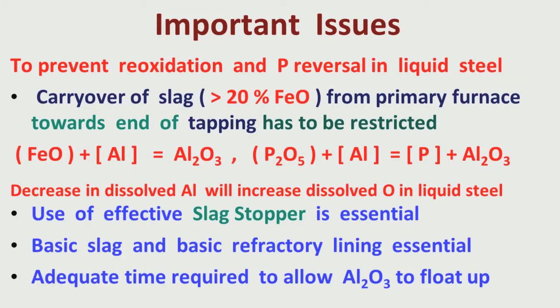Then I have also talked about some important issues of deoxidation. What are the issues? The carryover slag from the primary furnace. I have told you, towards the end of tapping there is a possibility of carryover because of funnel formation. So this has to be low, because this carryover slag, that means the slag from the primary steelmaking, is very rich in iron oxide, more than 20%, it may be 25%, it may be slightly more. Then there is about 5% MnO. Then there is maybe about 3% phosphorus oxide, which has removed phosphorus from liquid steel to the slag.